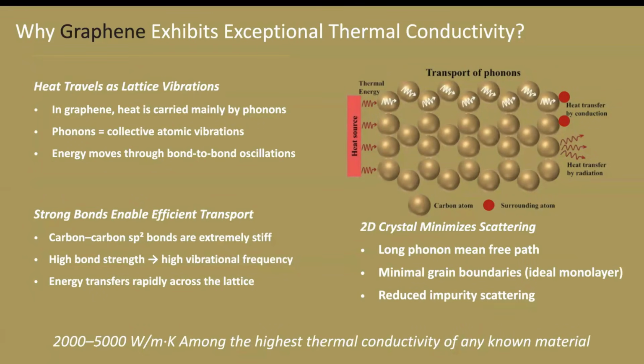So now let's talk about heat. In solids, when heat moves, it moves through vibrations. Like in atomic motion, these vibrations, or phonons, travel through the lattice and transport heat. Graphene's carbon-carbon bonds are extremely stiff, so when they vibrate at high frequencies and transfer energy, it is very efficient. And because graphene is a nearly perfect two-dimensional crystal, there are very few defects or grain boundaries to scatter those vibrations. So heat can travel long distances with minimal disruption.